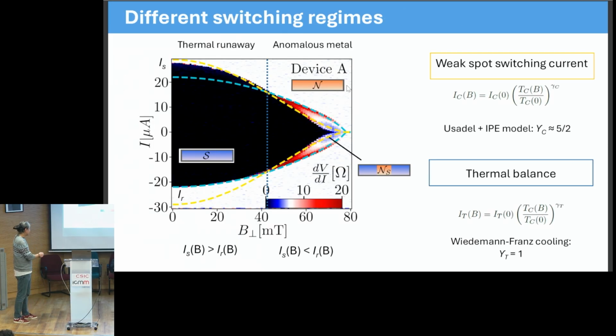I don't want to extend myself too much, but overall, what we observe is that this wire can have different phases. When we have the normal contact deposited on the superconductor, we will create a local weak spot due to the inverse proximity effect. And when we start ramping the current, the first part of the wire that will turn normal is this weak spot. And then two different things can happen.